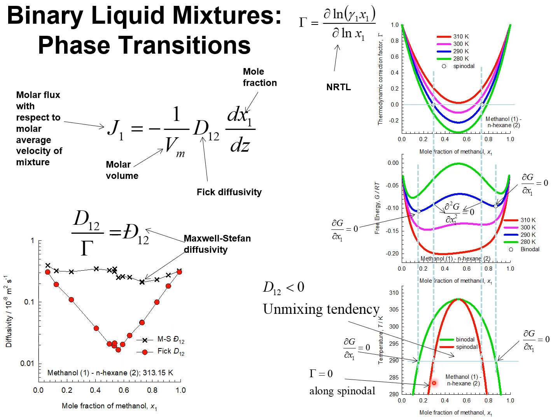Within the region, the mixture will undergo phase splitting. Say if we take a composition here of 0.5, subject to a small perturbation, the mixture will yield a hexane-rich phase and a methanol-rich phase. The area between the spinodal curve and the binodal curve is a metastable region.